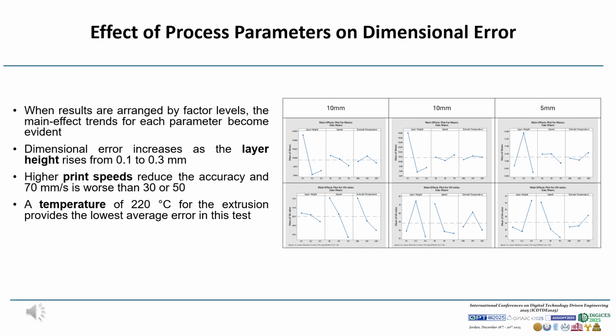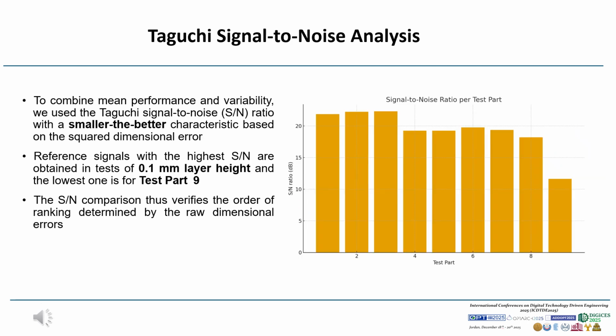lowest average error. To account for both the mean performance and the variability, we also evaluated the Taguchi signal-to-noise ratio with a smaller the better characteristic. The highest SN ratios are obtained for conditions involving 0.1 mm layer height, which means these settings are not only accurate on average but also most robust. The lowest SN ratio corresponds to test part 9, confirming that this is the least